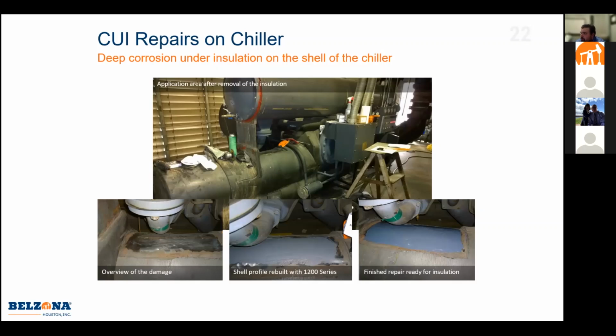So this is an area where we couldn't really blast based on the customer's parameters. So as you can see on the bottom, we put a grind on it with a Dremel and a grinding rock. And this one we used a Belzona fast curing epoxy with a reinforcement. It basically gave it a little more structural integrity back to the pit fill. And then after that, we put some of our epoxy over that for even more CUI protection. And this was all done within 1 day. So it's a very fast, very quick repair.